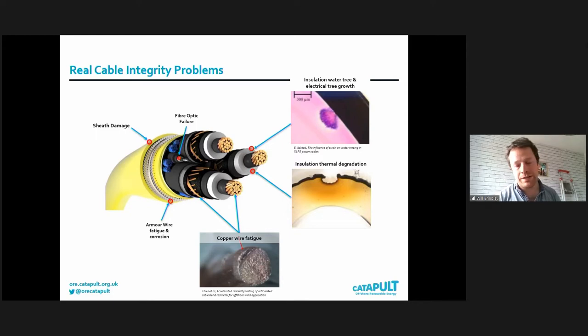But certainly what we've seen from our tests, but also the data published in the industry, is the highest risk component are these copper wires, particularly the screen wires and the copper cores. Because when they cross over each other, you get this kind of fretting effect where you have a crack initiation site. And that crack can quite easily propagate and cause failure, and that's what we're seeing. So design of those copper cores is important.